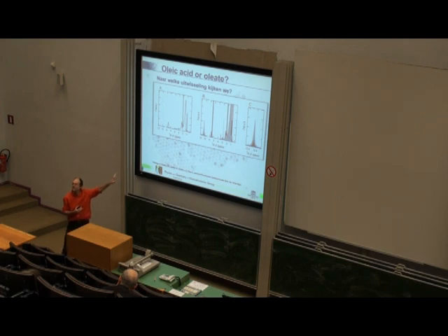You will say, okay, you see a little bit of protons there coming up. The problem is, we have to make this deuterated acid ourselves. So it's never perfectly pure. The nice thing is we can use NMR to determine the purity. And so we can actually calculate, depending on either scenario A or scenario B, given the purity of the deuterated acid, how intense this signal should be.